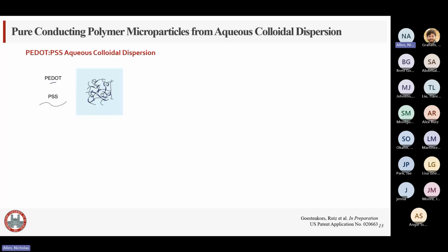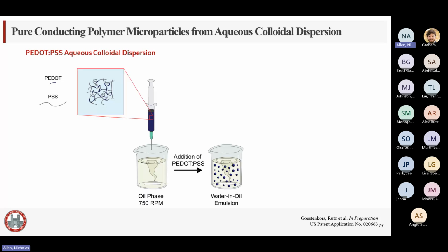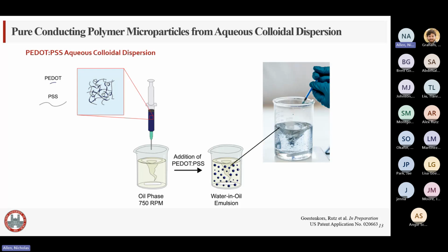So my idea was, why not use PEDOT:PSS aqueous colloidal dispersion, a large amount of water, as the aqueous phase in a water and oil emulsion, add it to the oil, introduce a stir bar, break it up, and then raise the temperature to induce cross-linking of the PEDOT:PSS droplets to form PEDOT:PSS microparticles in the oil. And upon addition to the oil phase, PEDOT:PSS under shear turbulence did create these aqueous micron scale droplets within the oil. However, our next question is, what temperature do we use to cross-link these PEDOT:PSS droplets into PEDOT:PSS microparticles?